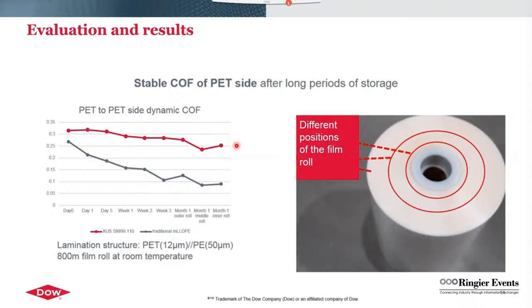For the roll stored for 1 month, the film sample was collected at different positions of the film roll: outer, middle, and inner. It was found that with the metallocene LLDPE sealant, the COF of the outer PET surface decreased to below 0.1 at the middle and inner positions of the roll after 1 month of storage, while with the COF stable resin XUS 59999.110, the COF was maintained around 0.25 at the same positions. With the more stable COF of the outer PET surface achieved with the COF stable resin XUS 59999.110, it can help to improve the runnability of the film on the automated packaging machines and increase productivity.